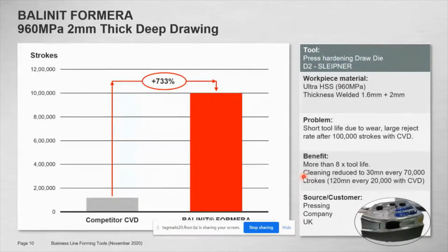Another example for BS6 standard automotive, we have high strength steels. So this is an example of 960 megapascal, 2 millimeter thick deep draw. Here, of course, the competitors were providing CVD treatment, which is chemical vapor deposition, which was commonly used in the past. But with our solution of BALINIT Formera Advanced, we could give almost 8 times tool life to the customer. So short tool life was the major problem, and here we gave more than 8 times, and this is a customer in our UK facility.